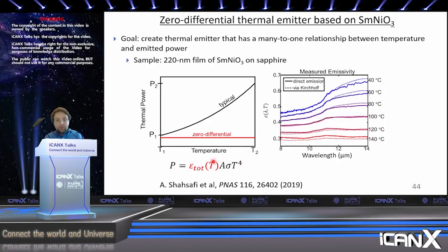And fortunately, we were able to do just that with a thin film of samarium nickel oxide, this nickelate material that I showed you just a few slides ago, on top of a sapphire wafer. Here's a measurement that we did. This is the spectral emissivity versus wavelength versus temperature, measured using a couple of different approaches: via direct emission measurements using our calibrated system, and also using Kirchhoff's law of thermal radiation based on our ellipsometry data. And you can see that this emissivity at all of these wavelengths in the long wave atmospheric transparency window gradually decreases with temperature, which is exactly what you need.